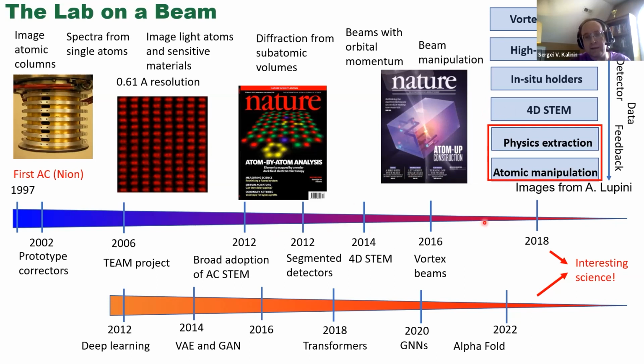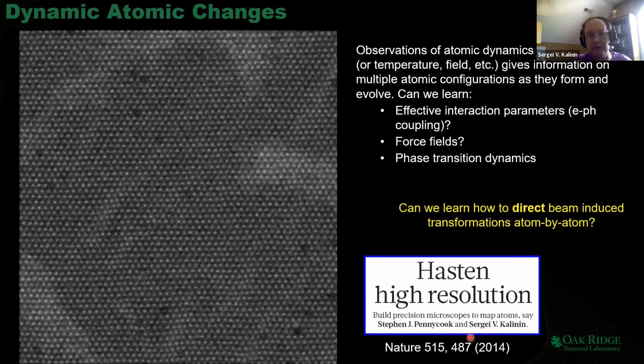In fact, over the last 10 years, there was a veritable revolution in the field of electron microscopy with the near constant emergence of techniques such as electron energy loss spectroscopy that I've shown, techniques such as the diffraction from subatomic volume, what is now called 4D STEM, and the emergence of the probes such as beam with the orbital momentum, when you can measure the orbital momentum or spin of the materials. And what's also very interesting is that this last 10 years of the development in the electron microscopy have been paralleled with the unprecedented growth of the deep learning techniques. And I will show you how these two techniques can naturally complement each other to make a sizable difference in how we can build matter on the atomic level.